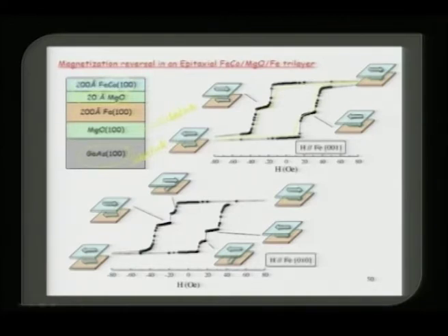In such a situation, if this layer and this layer are ferromagnetically coupled, you see the saturation reached very fast. As you come down to this staircase you can see that the layers are antiferromagnetically coupled, and as you come down further, the top layer gets rotated, therefore you again see a fully ferromagnetic layer at say 80 oersted.